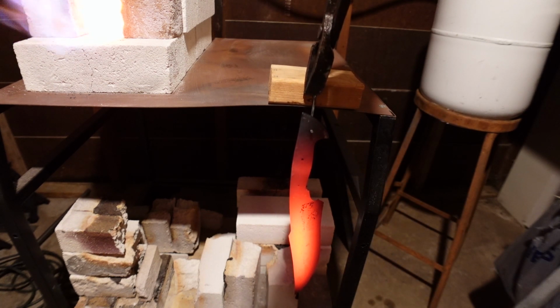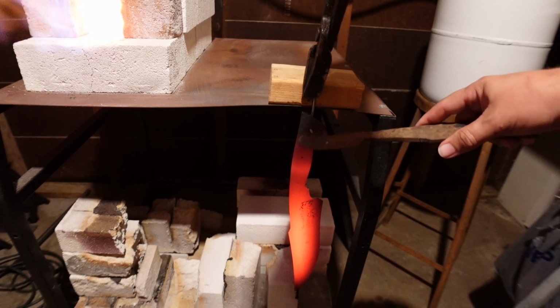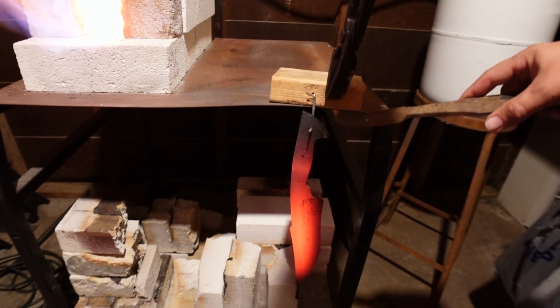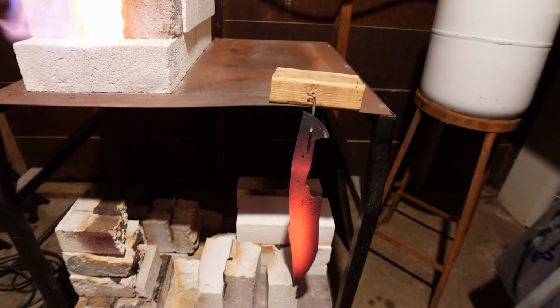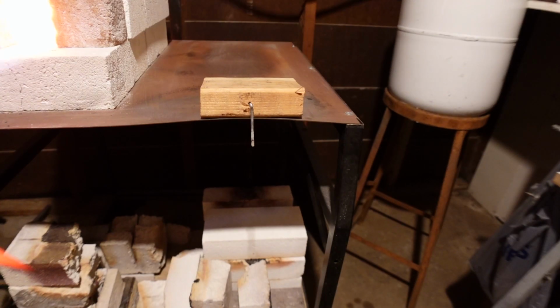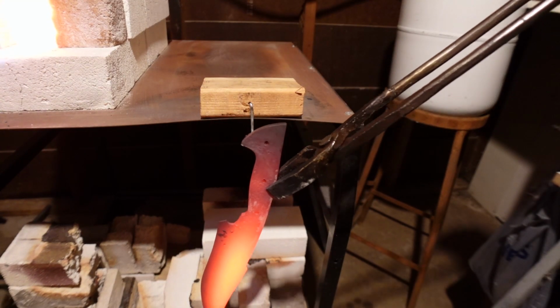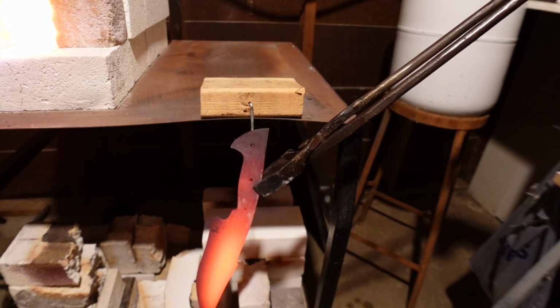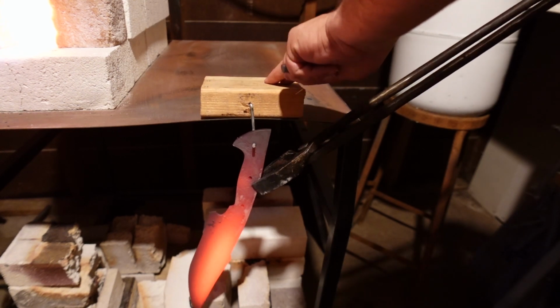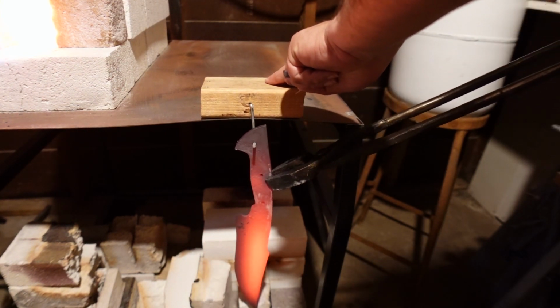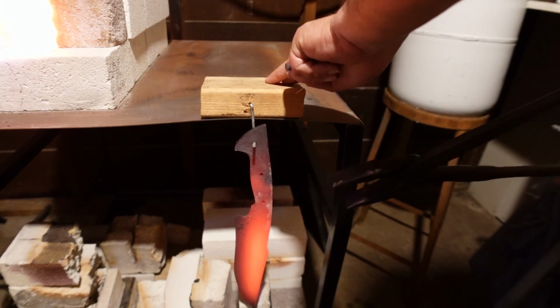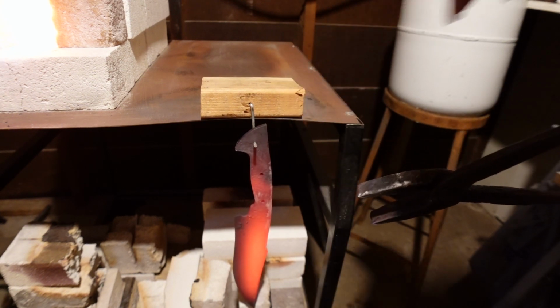So I did have to mess with this a little bit too much each time I did these normalizing. Now, other than that, everything else worked how it's supposed to, but the second heat, we did bring it up to right at about 1500 degrees and let it cool in still air. Still air is important because 5160 can air harden a little bit, and you don't want that to happen.